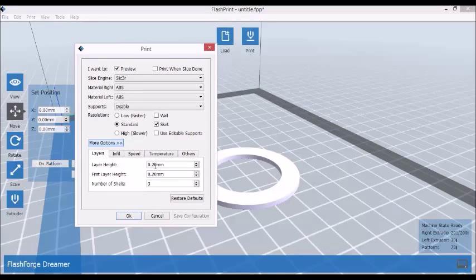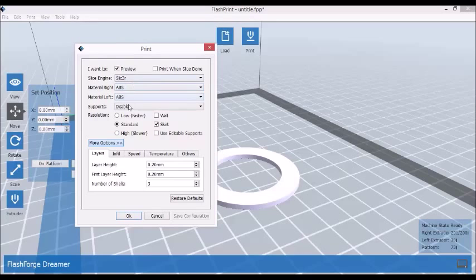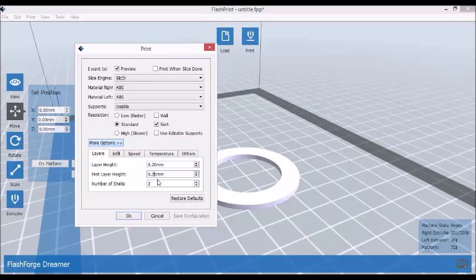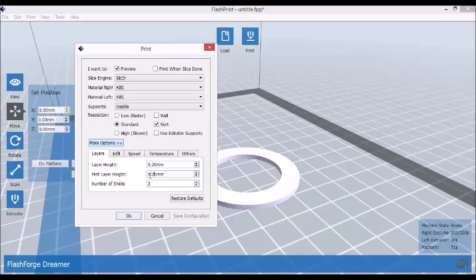So when you set up print, go with the standard settings, it doesn't matter if it's ABS or PLA, we're changing settings anyway. So with the layer thickness, I recommend going to 0.2 and 0.2. Keep in mind that the thicker the layer, it might appear faster printing, but you have to reduce the speed because when you increase the layer thickness, extruder has to push more filament out. So it will cause issues. So go with 0.2 mm. If you go thinner, I experienced before that the nozzle would drag the print after itself and it would just simply destroy it.